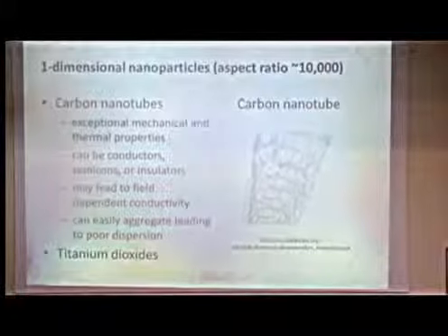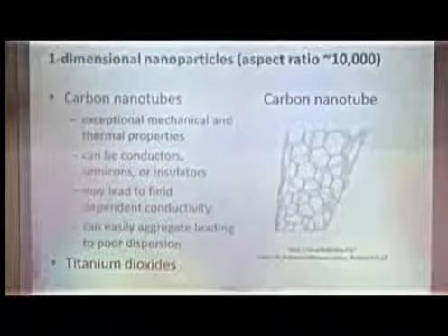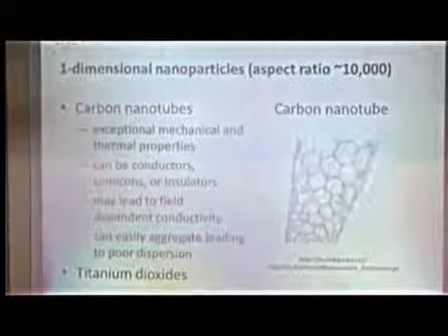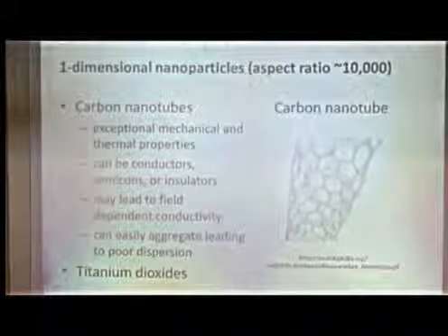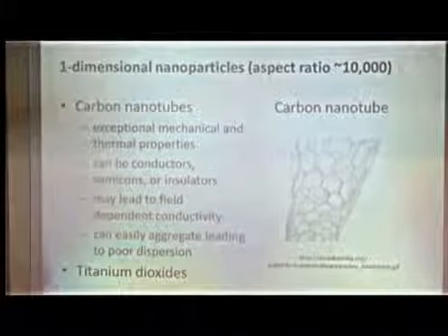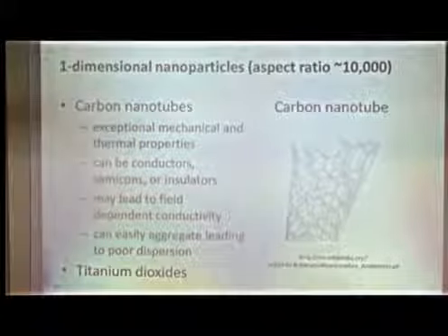And one would assume that if you're going to put a relatively conducting one-dimensional structure into a nice, beautiful, well-insulated, low permittivity host material, then you're likely to have some problems with field enhancements at the ends of the materials. And as far as I can see, less work has been done incorporating these very high aspect ratio nanoparticles into the host materials than many of the others.